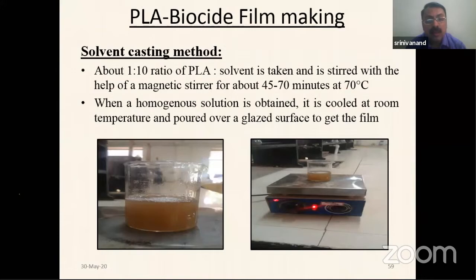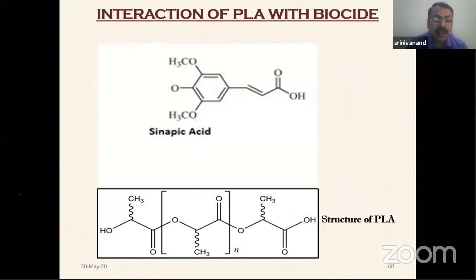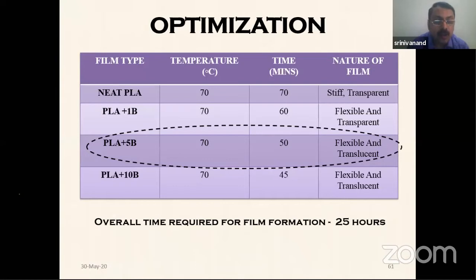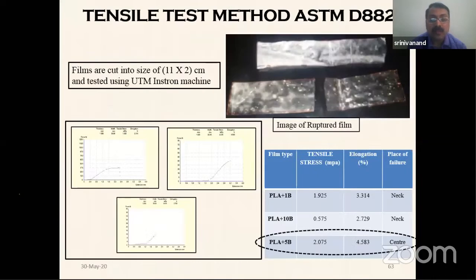Similarly, we made PLA biocide films using the proprietary biocide which I indicated. As I told you, the main ingredient of the biocide is phenolic acid, and the structure of PLA is indicated below. We found there is a chemical interaction between these two, and we were able to optimize the percentage of biocide in PLA. It is 5%. 5% of biocide in PLA exhibits a better set of properties. We can see the 5% biocide improves the mechanical strength to a greater extent, with elongation at break as well.